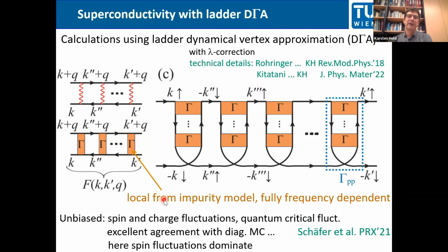So the next thing we are doing is a dynamical vertex approximation, more precisely a ladder version of that with a lambda correction. What is it doing? So you all know random phase approximations. There you just have a geometric series, a ladder of bare Coulomb interactions. And if you do RPA, you can describe antiferromagnetic spin fluctuations and how they give rise to superconductivity. But it also very much overestimates antiferromagnetism and superconductivity. So in RPA, it's no problem at all to get a room temperature superconductor or even 1000 Kelvin. And what is wrong here in the RPA is there is no screening of this bare Coulomb interaction. It's just way too big.